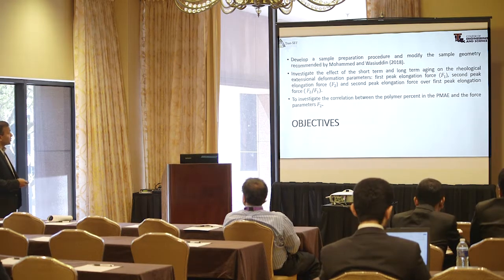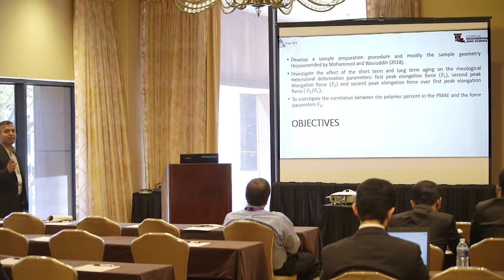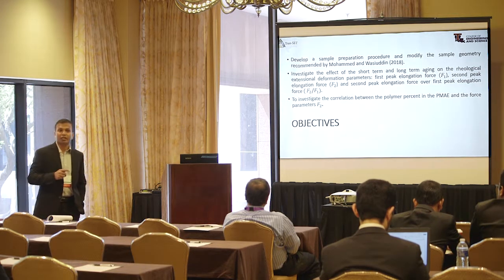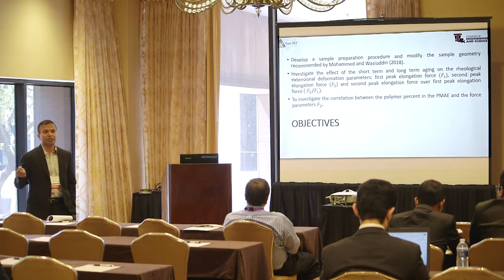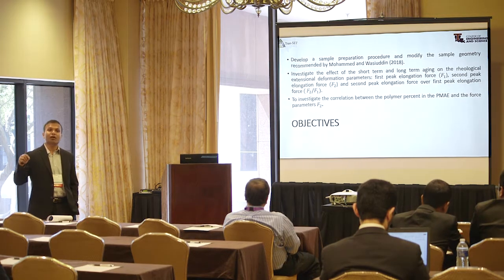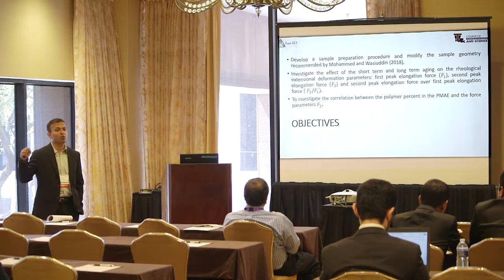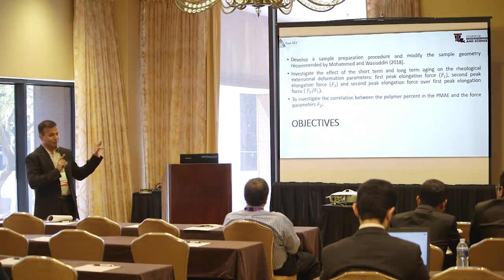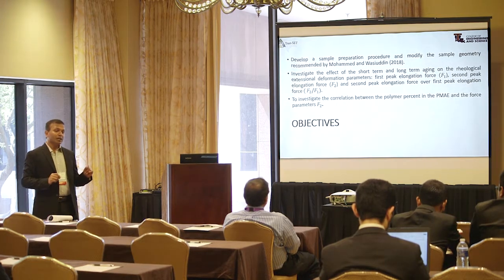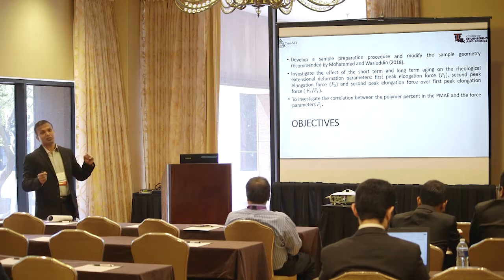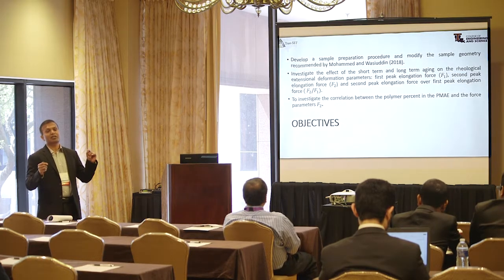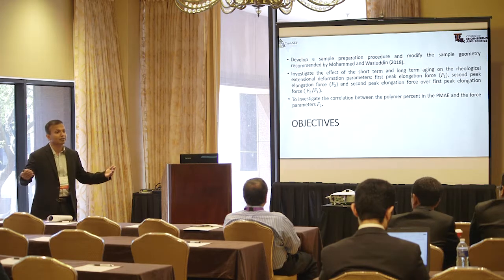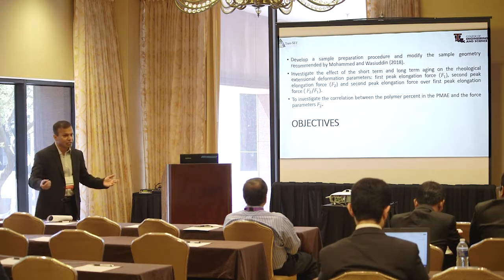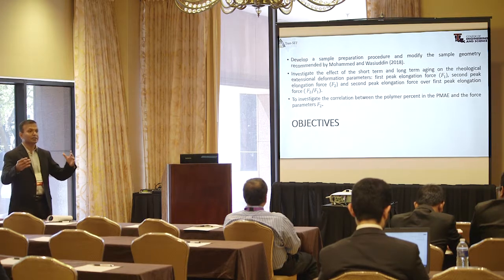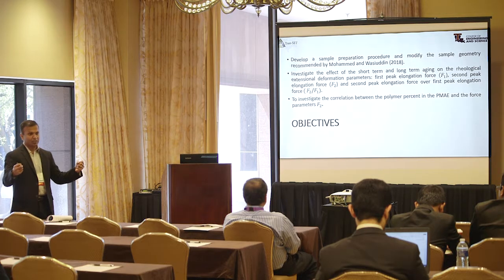So then, when we didn't get a correlation, all of us are familiar with R-square values, we found that the R-square value is 0.5, 0.6 with the force ductility parameter. So what we did, we tried to find out how we can capture the extensional information. So we went to a new method, how we can use the DSR machine and do the extensional test.